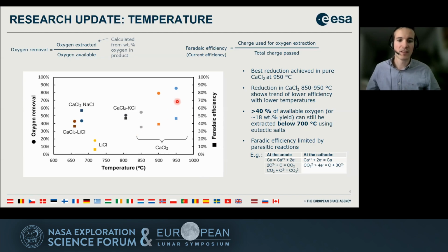What you can see here is that with pure calcium chloride, our baseline, we are close to 100% reduction, with close to 90% in this 24-hour baseline. As we reduce the temperature, we also lose efficiency, getting closer to 50% removal at 850. But by using eutectics, we stay in this band of 40 to 50% reduction while still lowering the temperature. So now we have a process which can extract 40% of the oxygen in the lunar regolith below 700 degrees. If you compare the yield you can have with hydrogen reduction or carbothermal reduction, that's in principle much better.